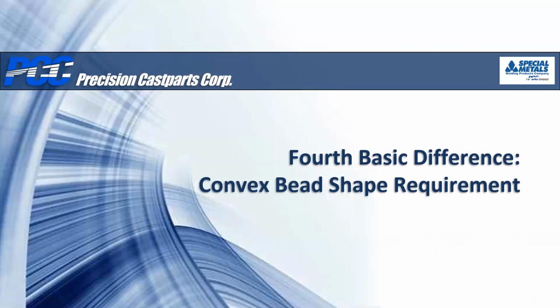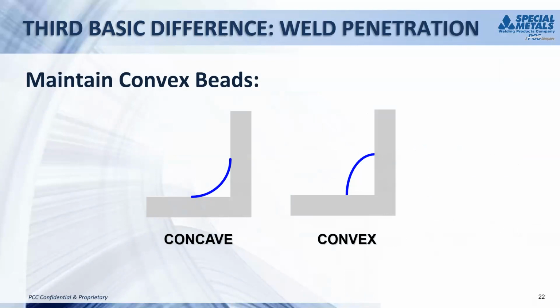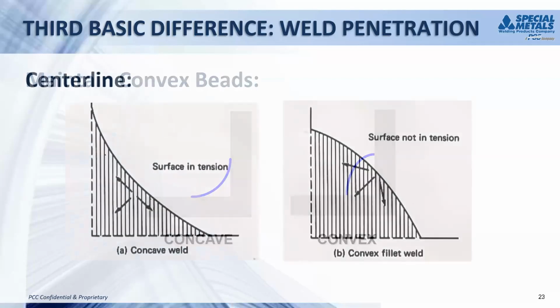But the fourth basic difference is the convex bead shape requirements. With a concave bead shape, you're extremely subject to centerline cracking. And the same is true with craters. You might make a beautiful convex weld, and then if you stop and just break the arc abruptly, you have a crater and you get cracking. So you need to make all parts of your bead slightly convex. And if you have a bead like the one on the left, you need to slow down. Next, John.